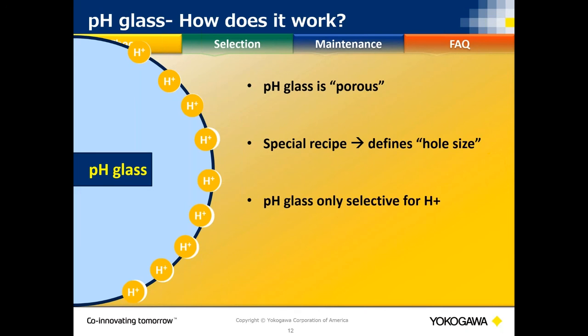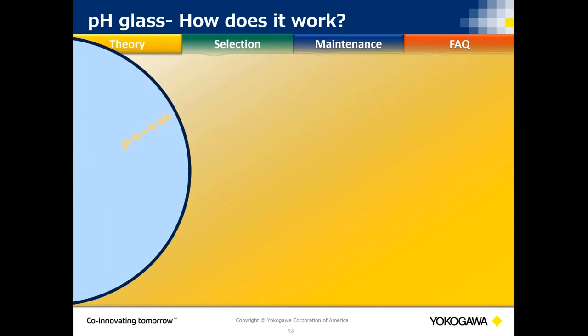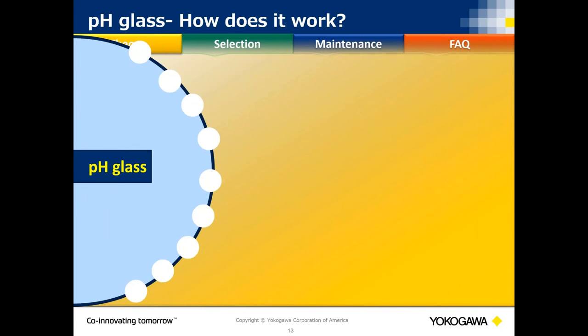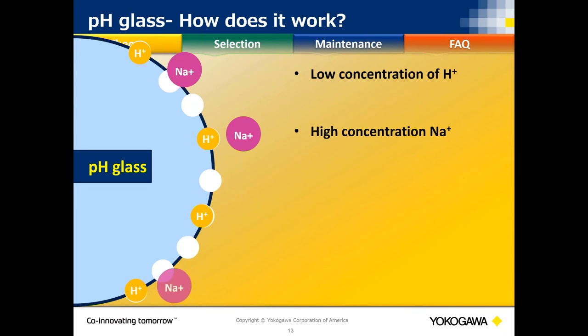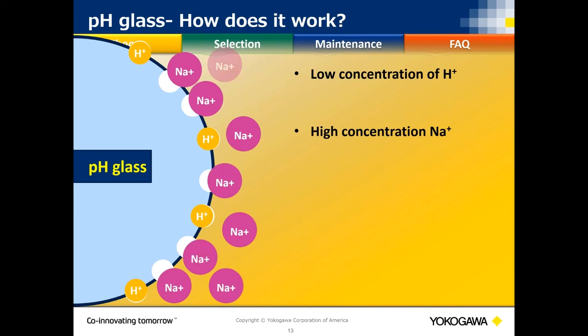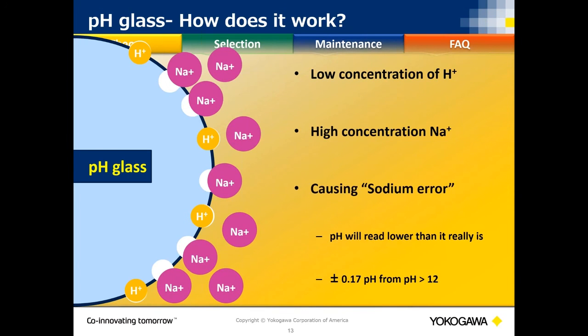2 things to consider though. 1, what if you're in a caustic solution, okay? Caustic solution meaning like sodium hydroxide, for example. You still have the same measuring glass, but there are very low levels of hydrogen ions, or it's a very low acid concentration in the solution. You have, however, high sodium concentrations in your process. What happens is the sodium ions are actually bigger than the hydrogen ions, so they won't actually fit in the hole, but they actually line up along the glass electrode and kind of fake the glass electrode into thinking that